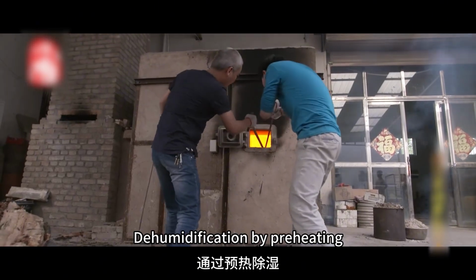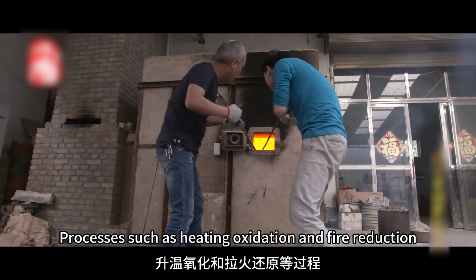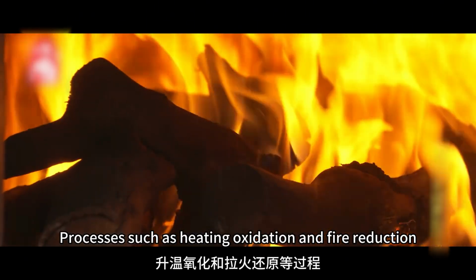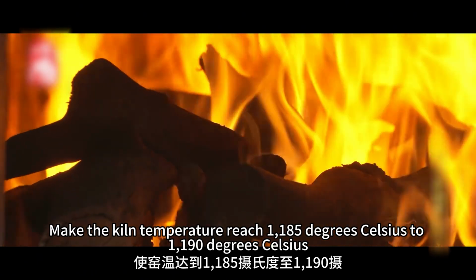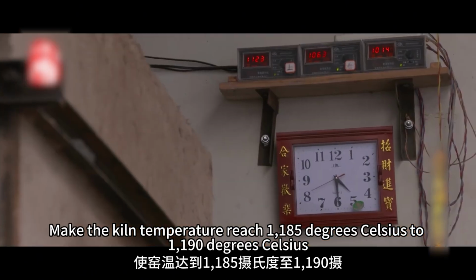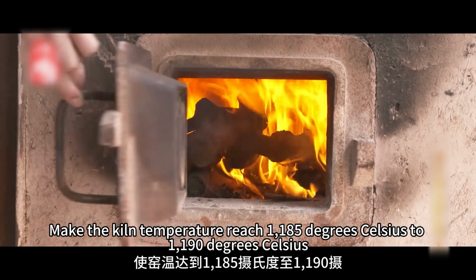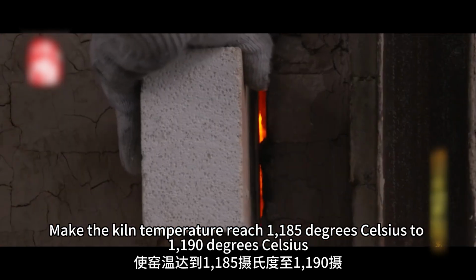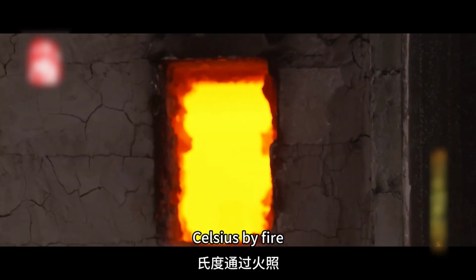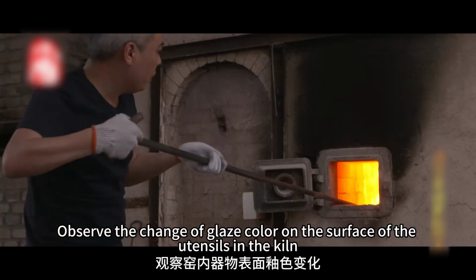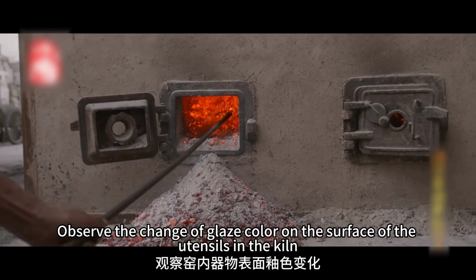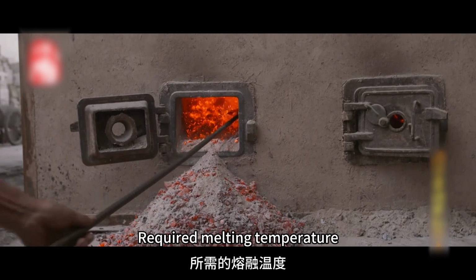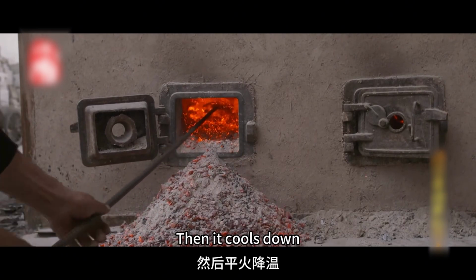Processes such as dehumidification by preheating, heating oxidation and fire reduction make the kiln temperature reach 1185 to 1190 degrees Celsius. By fire, observe the change of glaze color on the surface of the utensils in the kiln. Once the required melting temperature is reached, it then cools down.